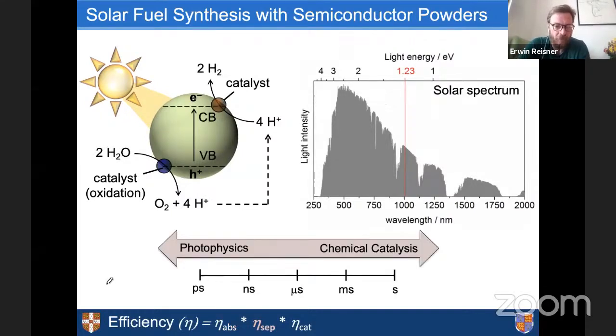What else needs to be considered for water splitting or photocatalysis in this context is the kinetics and this mismatch of very fast photophysics and slow chemical catalysis. Many of these photochemical or photocatalytic processes are on a very fast time scale, meaning picosecond to nanosecond, if you just think about the photo excitation and excited states. But these catalysts turn over very slowly. If we think about hydrogen evolution catalysts or molecular systems, millisecond, second, or longer time scales are very common. So in order to be efficient, all these excited states that are generated by the light absorption need to be used to do the chemistry that you'd like to see.